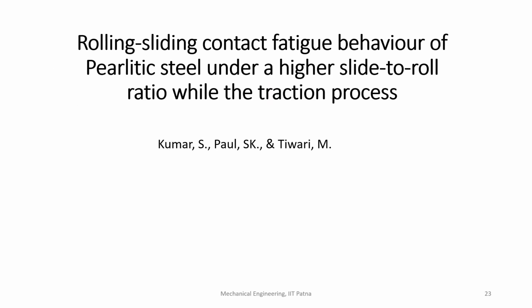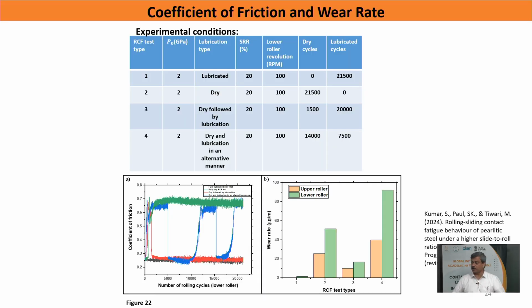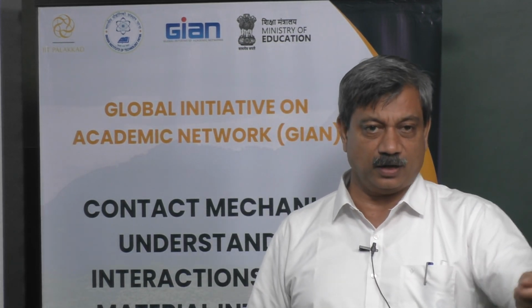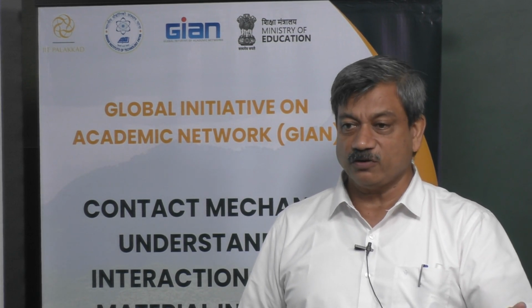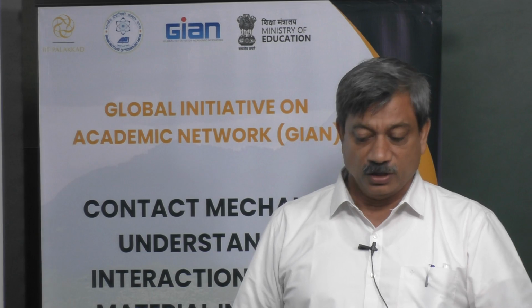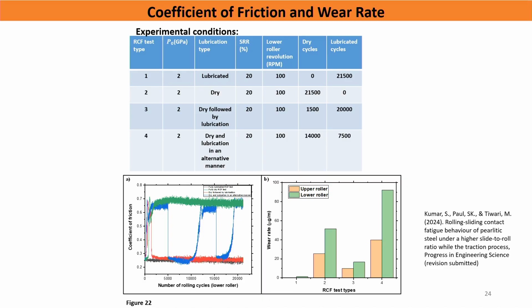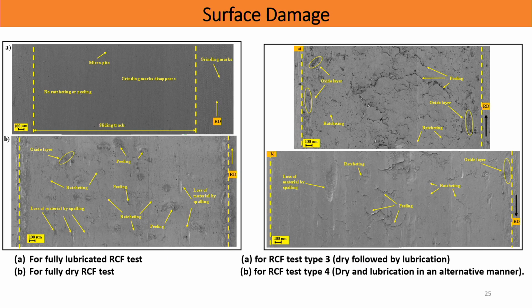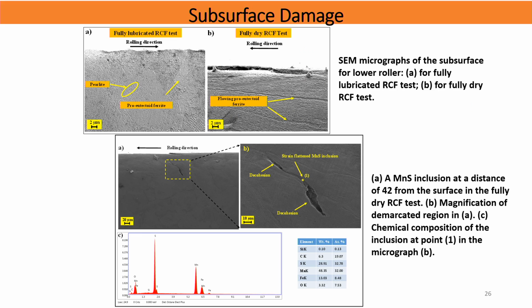So now, this is one test. We had 0% and 2% SRR. Now this is that extreme test we did with 20% SRR, a very difficult test to do because the tribometer shuts down. If you try it under boundary lubrication, there is so much vibration that it trips. There is an accelerometer, and if the vibration goes too high, it shuts down. So with 20%, we had a lot of issues, but we used to stop it, run it again, stop it, run it. And then we saw a lot more. Obviously, as we can see, the bending of the pearlite is going to be very, very strong here.